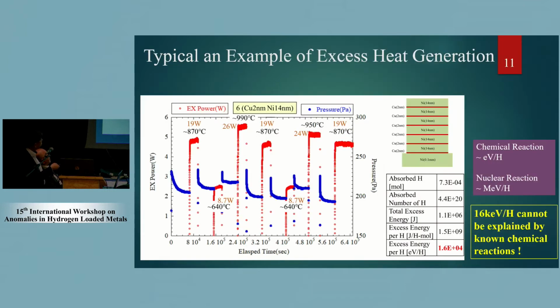Okay. This is a typical one, and I already showed it sometimes. In this graph, the blue point means pressure in the chamber. It's the pressure of hydrogen. At the beginning of the experiment, we gave about 230 Pascal, not so much. And the samples absorbed hydrogen like this.